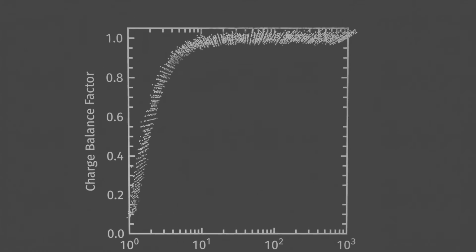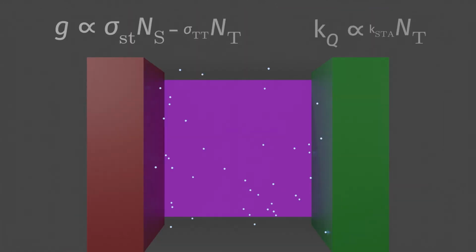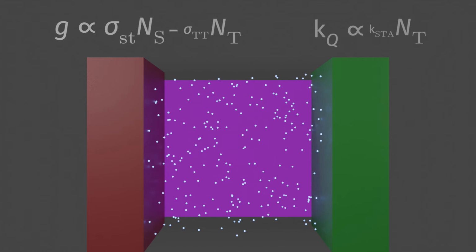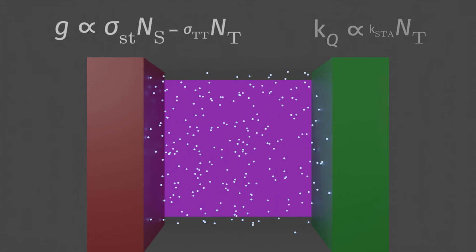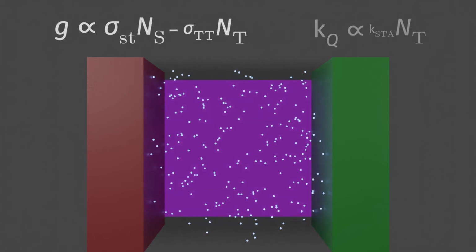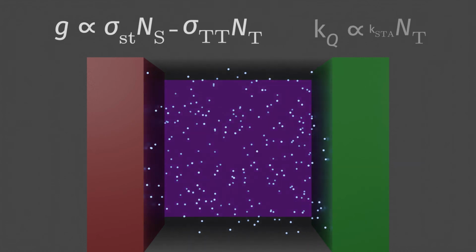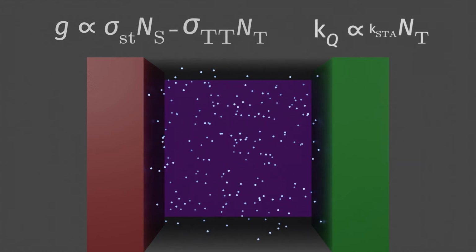Now with the position dependence, we can re-examine the absorption and quenching terms. While the uniform case of triplets is easiest to understand, this applies in the same way to our carriers. If the absorption cross-section is sufficient, it necessarily lowers the gain. But in this material, a higher annihilation rate by triplets would also be likely.